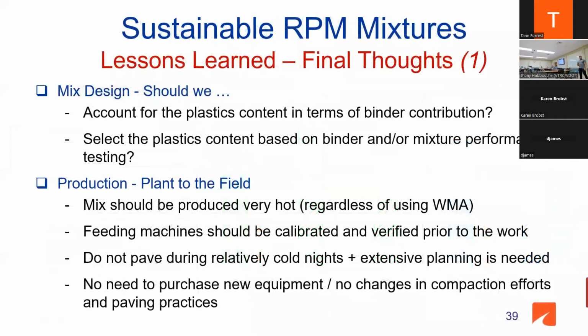So some lessons learned there: when we do the mix design, should we account for plastic as a replacement for aggregate, or as a replacement for the binder, or as a third component to be taken into consideration at the plant? We learned that yes, these mixtures have to be produced hot because the melting temperature of the plastic is much higher than the asphalt mixture. We need to have a good calibration of the feeding machine, so we make sure if we're applying 5% plastic into that mix, it's 5% within the first ton being produced as well as the last ton being produced on the job.